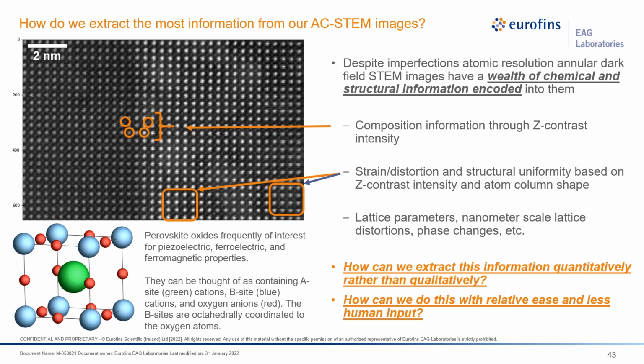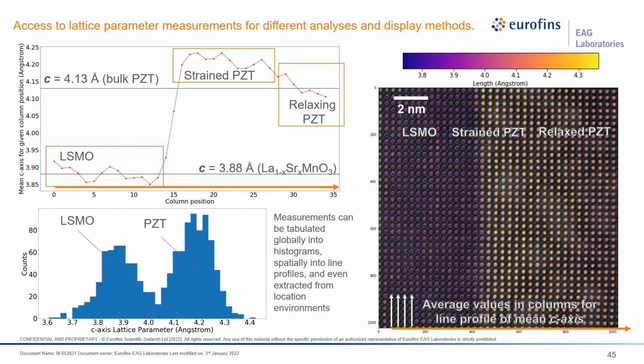Effectively, within these Z contrast AC STEM images, there's a wealth of chemical and structural information available. We can get composition information through the intensity from the columns themselves. We can also get things like strain, distortion and structural uniformity based on column shape. Things like the lattice parameter, nanometer scale lattice distortions and phase changes should also be available. And so really, how can we do this? Effectively, we can use computational image analysis to help us quantify these differences.